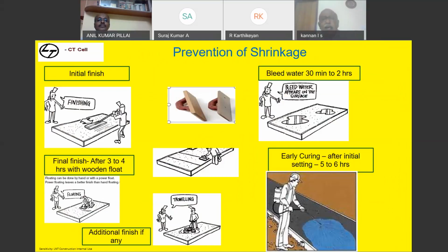Now, as I said, the finishing activity is the same. Do the initial finish, and please wait till the bleed water evaporates. Now the mason has to go only with the wooden float. This is the wooden float. Don't use any steel material. If you are using steel material, the surface will become smoother. The smoother the surface, the cracking tendency will be much, much more. You have to make it rougher. By using this wooden float, the wooden grains form thin grains on the surface of the concrete, so that the concrete surface is rough and it doesn't crack.